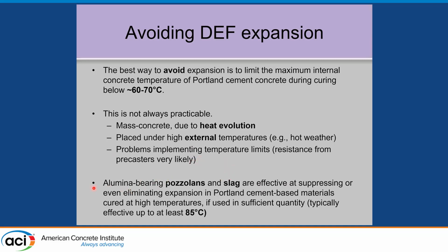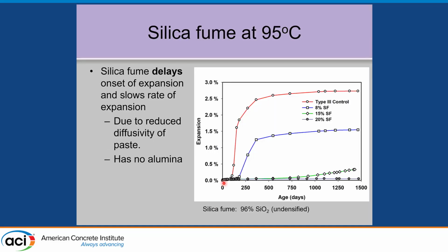But the other thing is that alumina-bearing pozzolans and slag are effective at suppressing or even eliminating this expansion at temperatures at least up to 85 and sometimes higher. And this is resulting largely from the study that I'm talking about that we did with Terry Ramlochan.